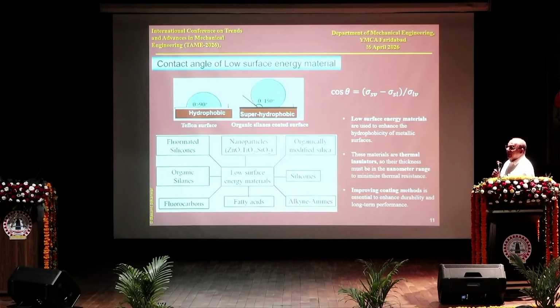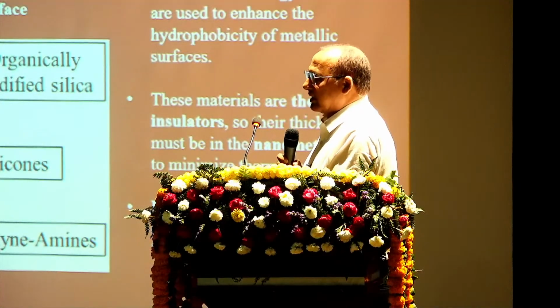But by nature, all these materials have low thermal conductivity. So coating thickness optimization is very, very important. If you take a large thickness, it provides additional resistance, which is not beneficial for condensation. If you provide a small thickness, there is a problem of leaching, meaning the coating leaches out, a stability issue or long-term stability issue. So making coatings and creating super hydrophobic surfaces on metal is one of the big concerns for researchers. Next slide.